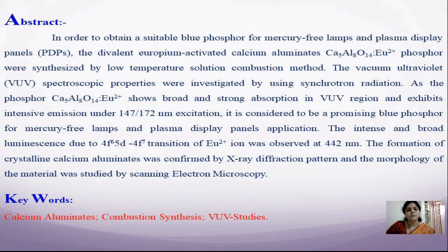The intense and broad luminescence due to the 4f6 5d1 to 4f7 transition of Eu2+ ion was observed at 442 nanometer. The formation of crystalline calcium aluminate was confirmed by X-ray diffraction pattern, and the morphology of the material was studied by scanning electron microscopy.